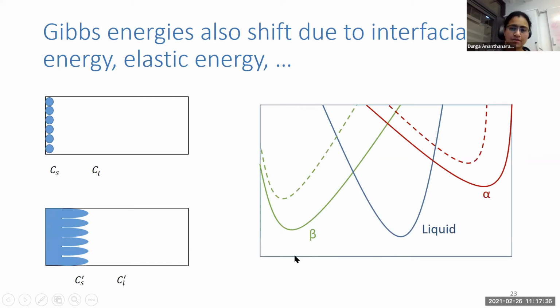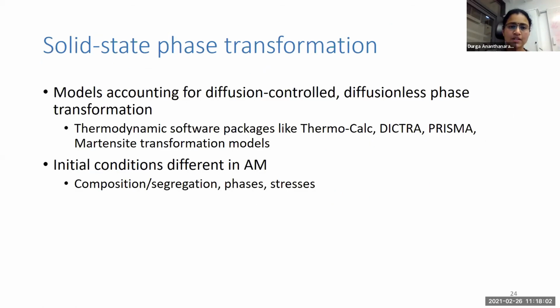But the Gibbs energy itself, what we looked at so far, if it's the bulk Gibbs energy, we know that when our system has different morphologies, like say cells, and you have other stresses in the system, then the Gibbs energy also shifts. So we have to add all of these additional energies to the system before we compute an equilibrium or any driving forces. So that also has to be kept in mind. So that was about solidification, all the different phenomena.